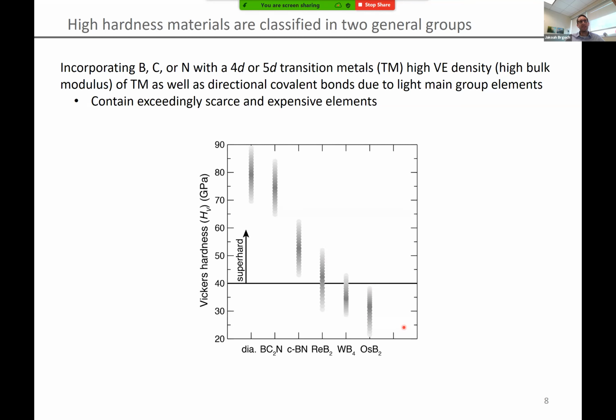Now, the hardness of the second type of material stems from the fact that you have a combination of 4D and 5D transition metals with a really high electron density, a high bulk modulus. If we're talking about resistance to indentation, it turns out there's actually nothing harder than having to push a valence electron into the core - the repulsive forces are just too high.